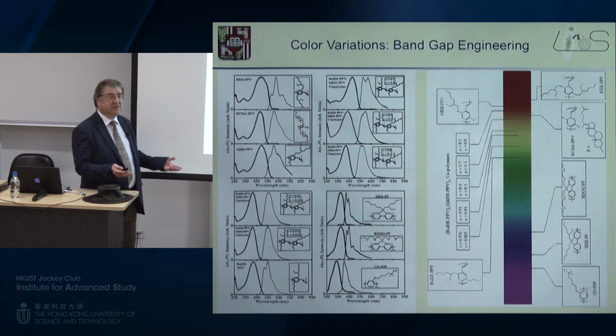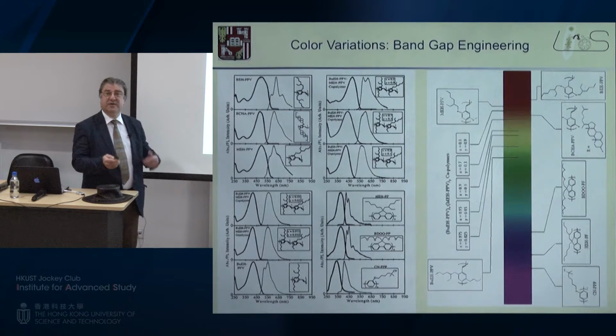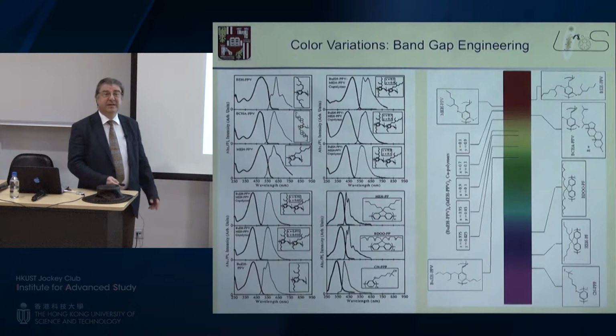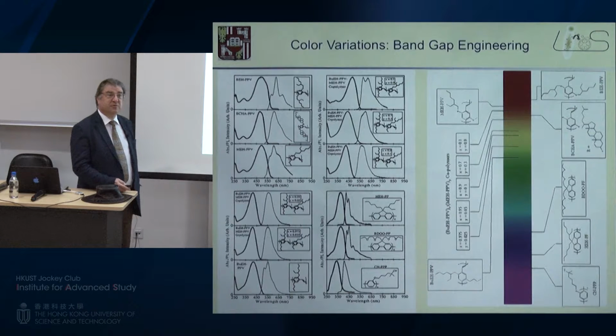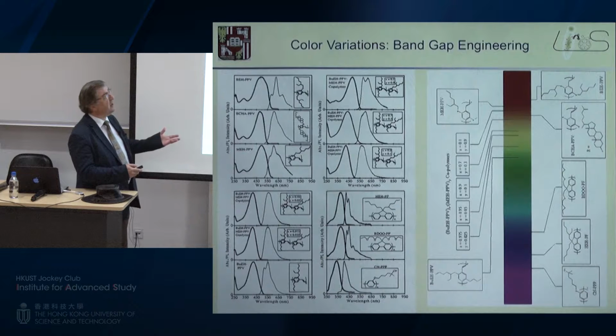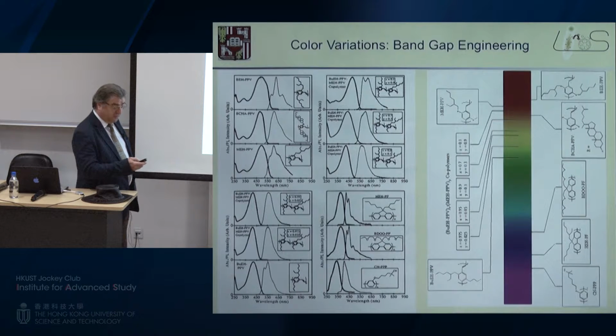You cannot do this with silicon. Silicon has indeed a 1.15 electron volt band gap, and this is it. There is nothing much to do about it. But here you can change the band gap over electron volts.